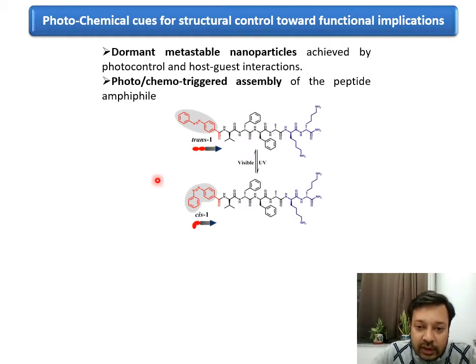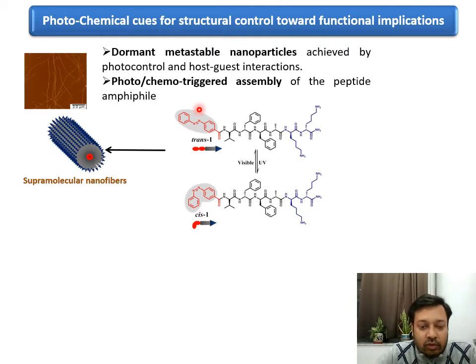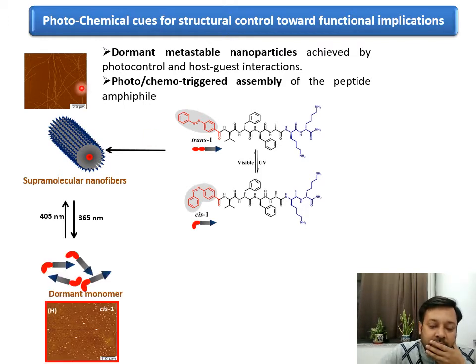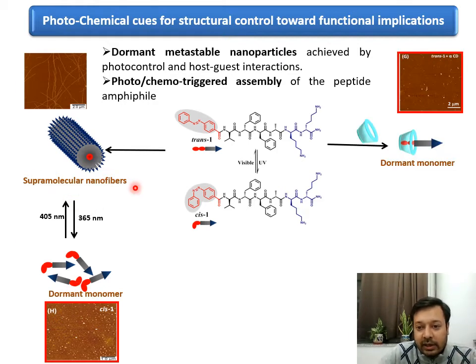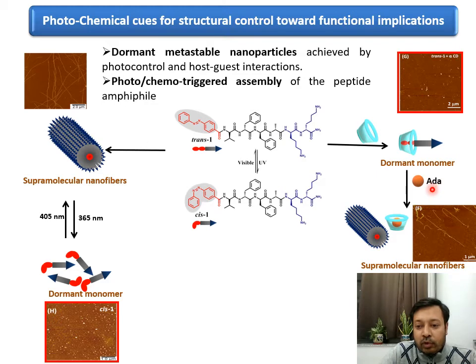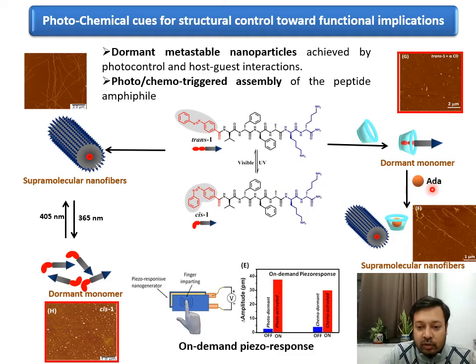Thus, what we have shown is that we can take this trans 1 fiber, it can grow into a supramolecular nanofiber, as you can see from AFM. You can use UV and visible light to get into the dormant monomer, and you can get it reversibly. Similarly, you can show that we can trap that in the dormant monomer state, and if you put adamantane amine, you can get very nice supramolecular nanofiber.